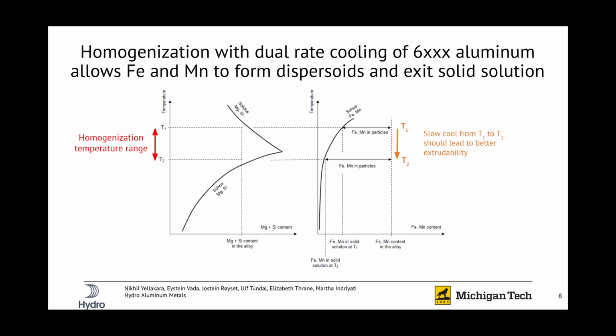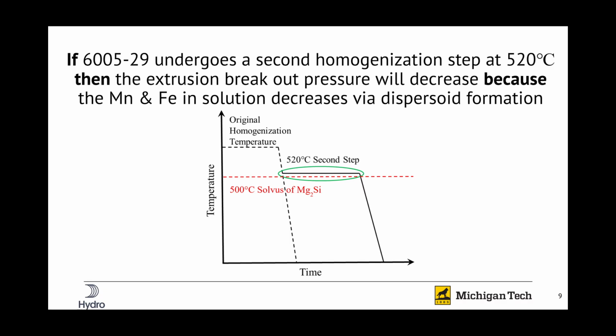And that brings us to our hypothesis statement. That is, if 6005-29 undergoes a secondary homogenization step at 520 degrees Celsius, just above the 500 degrees Celsius solvus of magnesium silicide, then the extrusion breakout pressure will decrease because the manganese and iron in solution will decrease via the formation of dispersoids, while not forming any of that magnesium silicide.